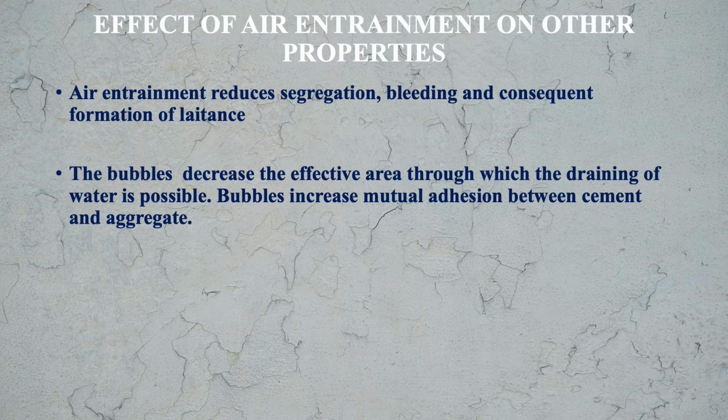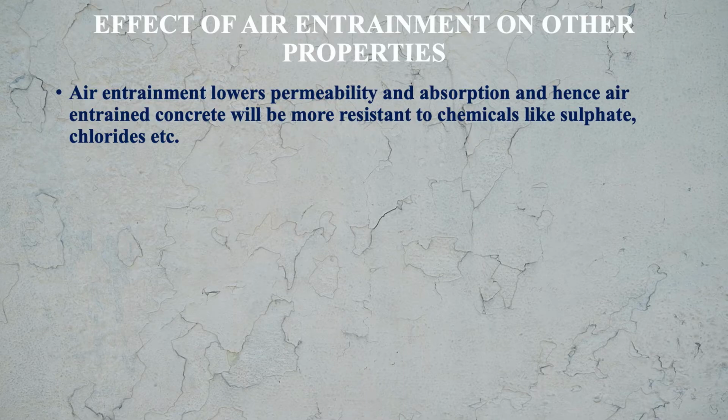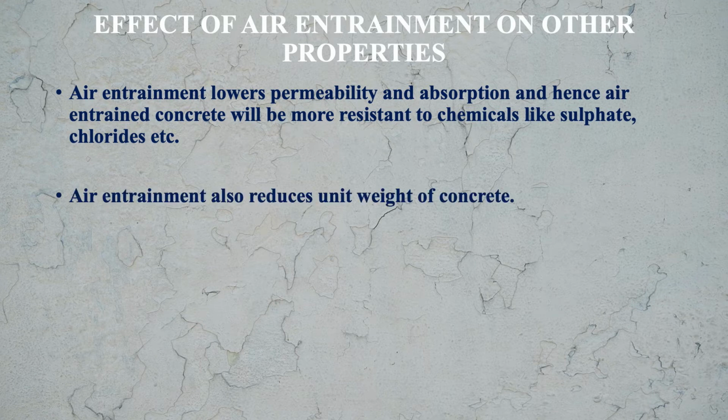Bubbles increase mutual adhesion between cement and aggregate. So because of increased adhesion, the segregation is reduced. Air entrainment lowers permeability and absorption, and hence air entrained concrete will be more resistant to chemicals like sulfates and chlorides. Air entrainment also reduces the unit weight of concrete, because when we are constructing structures with concrete, one concern is the weight of the material.